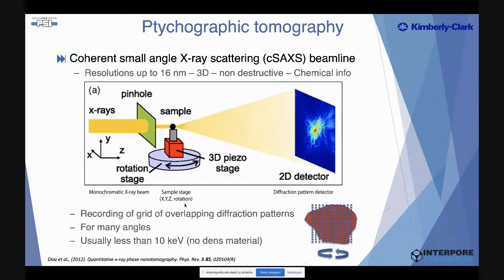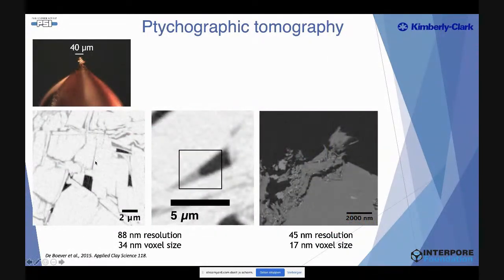But in principle, what you do is you record a grid of overlapping diffraction patterns for many angles, and this is all then stored in order to reconstruct your image at high resolution. So typically this only works for small samples. Our sample was 40 micron in diameter, but then we were able to go in 3D to a resolution of 45 nanometer. So you can see a lot of details. We could see also that there was liquid inside. You can even see the contact angle of your sample.